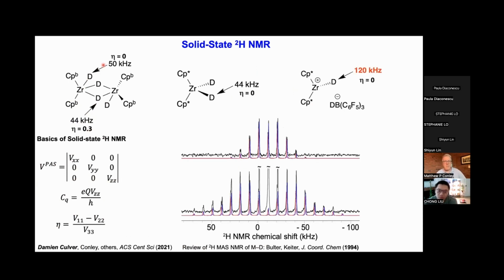So then we made the monomer, we ionized the monomer by just bulking up the CPs to CP stars. And you can see that you have this massive effect on quadrupolar coupling constants. So this is going up by a large margin. This isn't like some trick of hand. This is the powder pattern or the fitting for the raw data for the zirconium deuteride cation. This is what we see for the neutral CP star dimer. This is clearly narrower than this one.